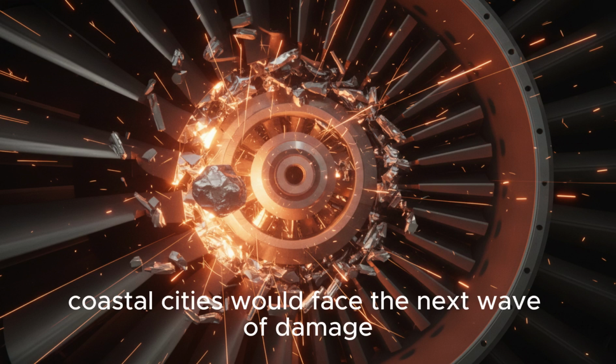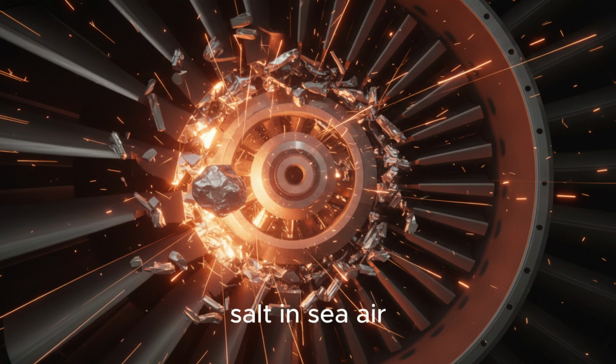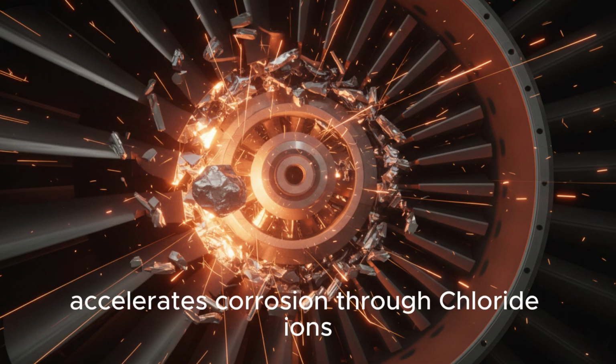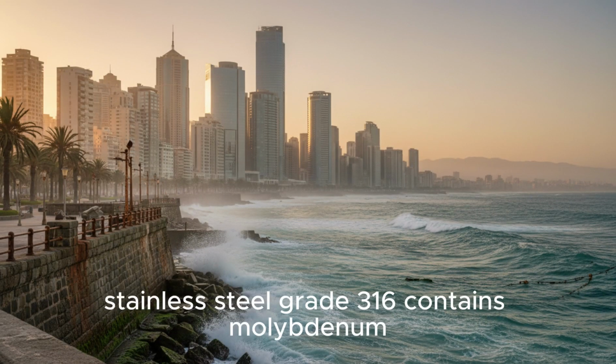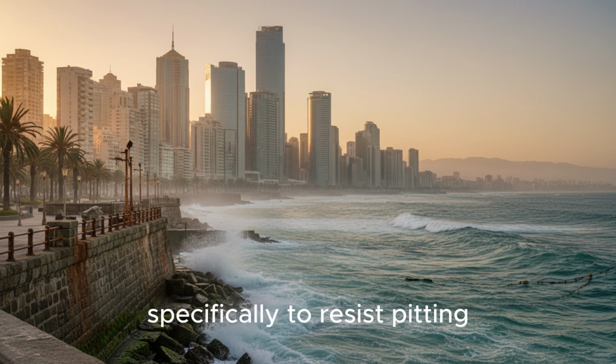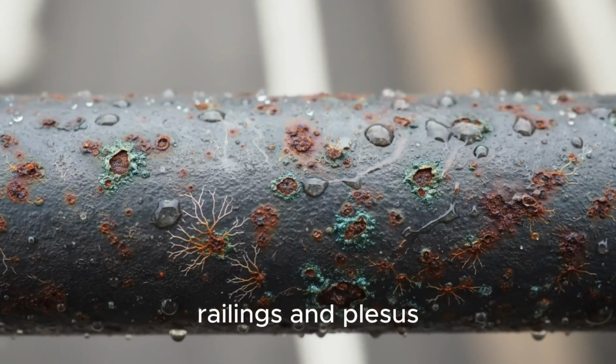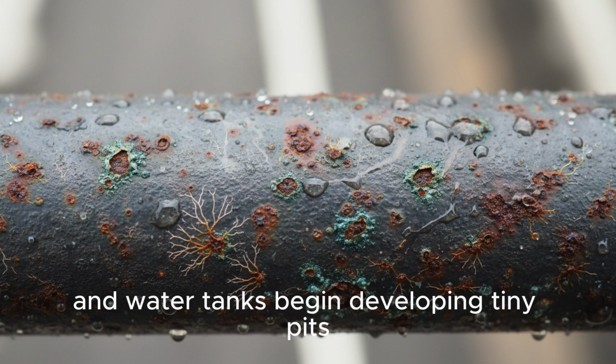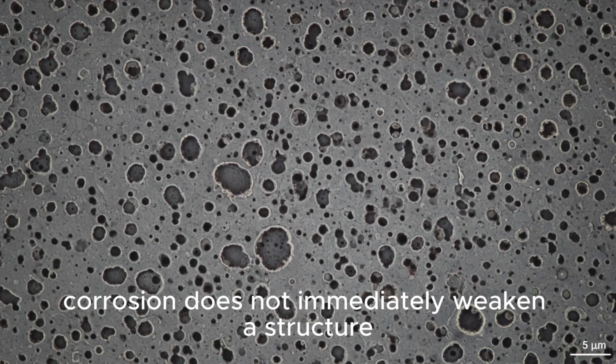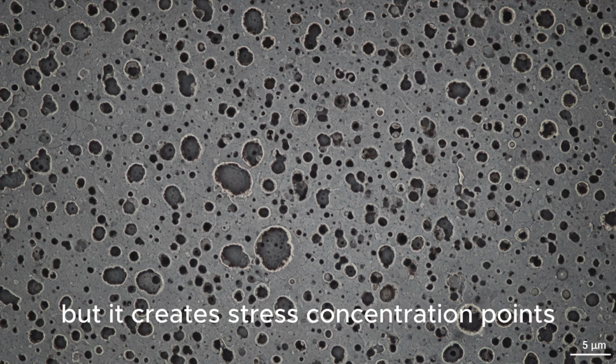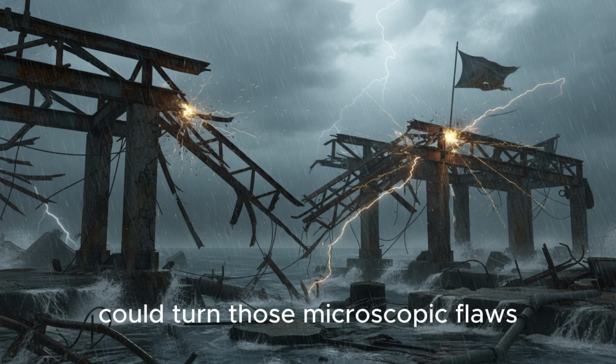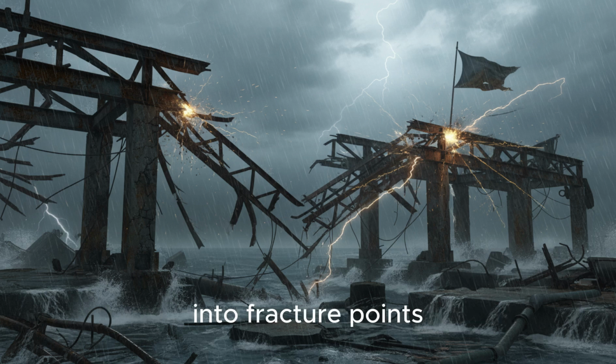Coastal cities would face the next wave of damage. Salt in sea air accelerates corrosion through chloride ions. Stainless steel grade 316 contains molybdenum, specifically to resist pitting corrosion caused by chlorides. Carbon steel does not. Railings, the structures along coastlines, and water tanks begin developing tiny pits. Pitting corrosion does not immediately weaken a structure, but it creates stress concentration points. A strong storm later could turn those microscopic flaws into fracture points.